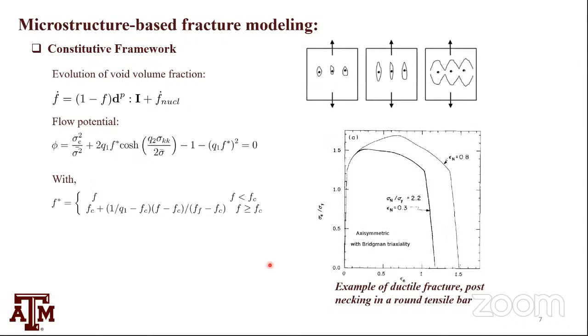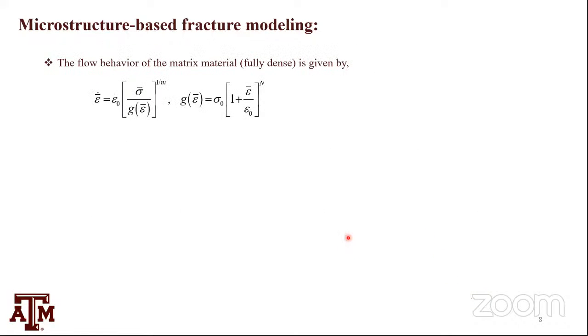All right, so when the yield function starts to collapse, just visualizing in simple uniaxial tension, I got elastic, yielding, strain hardening, ultimate tensile strength, then necking in an axisymmetric bar. Then I have this damage region where the voids start to grow. I reach this point where the majority of material points have reached f greater than fc. My yield function starts to collapse rapidly and the load bearing capacity drops rapidly, which basically mimics the creation of a new free surface or fracture. So with that, I need one more thing, the definition for plastic strain rate, which is a simple power law. It's a very favorite. And hardening is, again, a simple power law, metallurgically very old. So we put these two things together, easy.